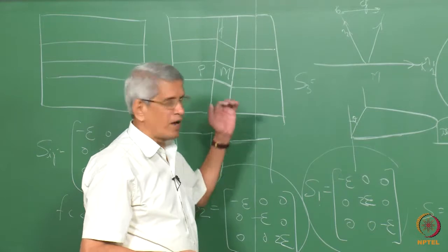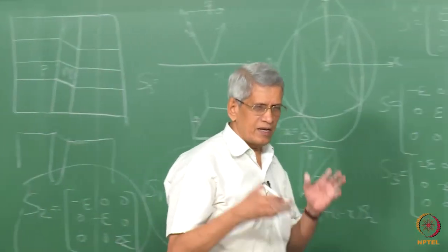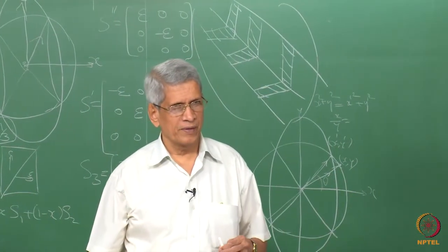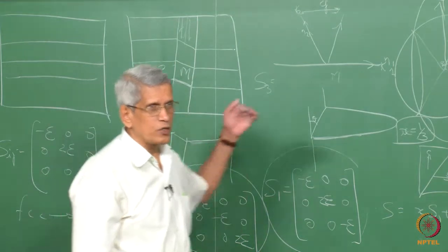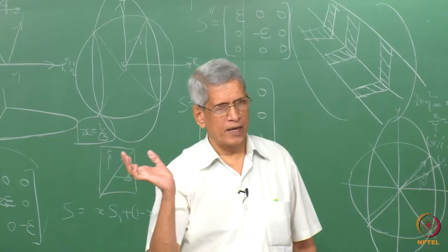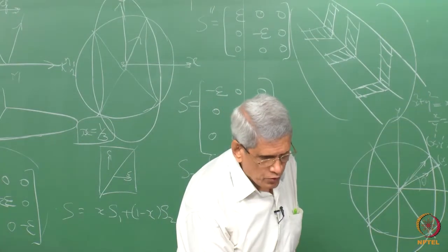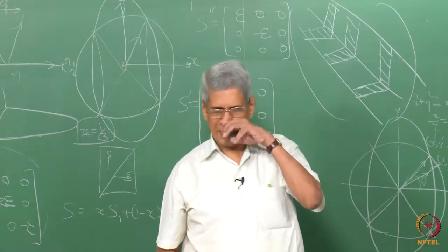What is the surface relief which we measure, from which can we find out the macroscopic strain? Because this shows that in this direction there is a homogeneous deformation. That is why it is a perfect, continuous line, correct? Otherwise, if any slip had taken place, a discontinuity should have been seen. Since we do not see that, that is how we can understand.